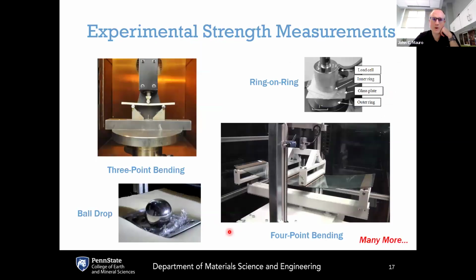Now, there are many different ways to measure the strength of glasses experimentally. Some of the common tests are shown here. That includes 3-point bending tests, 4-point bending tests, ring-on-ring tests, and the highly scientific ball drop test, where you drop a steel ball from various heights and measure the probability of failure.